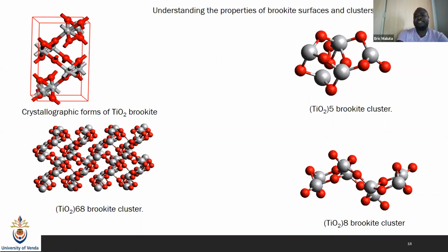Apart from looking at the surfaces and the bulk structure, we went further and looked at the nanoclusters, where we're building the nanoclusters by using different Ti elements. And as it is 1:2, normally on my right here, we have the Ti5 Brookite cluster, where we have 5 Ti, and the other one is the Ti8 Brookite cluster, where we have the 8 Ti elements. And the other on my left, below, is the bulk structure, which has 68 Ti elements. Then it means the oxygen is 2 times the number after the brackets, because it's 1 to 2.